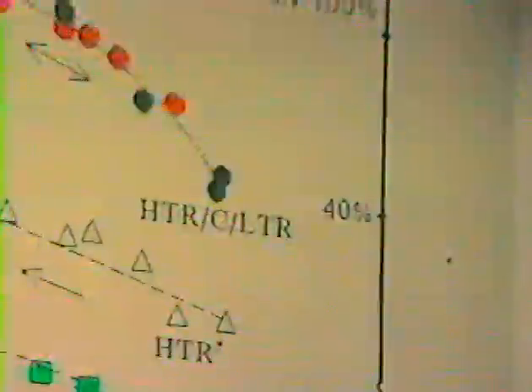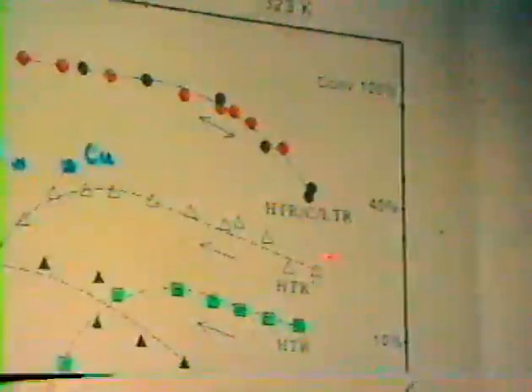To try to understand this in somewhat more detail, we looked at different pretreatment conditions. And I think the most important thing that I want to point out here is that this was the data from the preceding slide, the most active catalyst system. And again, as we got above 100 degrees, it deactivated irreversibly, as shown here. Now, interestingly enough, if we took this catalyst and gave it a high temperature reduction at 500 degrees, followed that with a calcination in 10% oxygen at 400 degrees, and then re-reduced the catalyst at 200 degrees, we enhanced the activity significantly, by close to an order of magnitude.